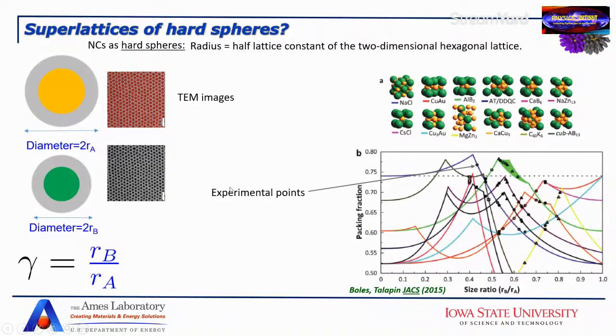So what we see here is that billiard balls are actually a good approximation. It's a good thing. It predicts something, but it is not quite there yet. Because, for example, this is good, but you also have others that happen at very low packing fraction, and that is something that we need to understand. So you see here that they are close to the maximum, but you also have some that happen at very low packing fraction, and this is unphysical. So the first step of modeling this as billiard balls is successful, but only partially so. There are many things that cannot be explained. Also, this maximum of the packing fraction happens below the line of the FCC. So in other words, this system in principle would be more efficient by packing two single component systems.